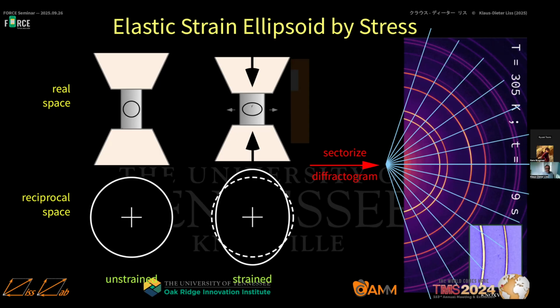In reciprocal space, remember, it's 1 over d or 2 pi over d. That means it becomes shorter in real space in the vertical direction. It becomes longer in the reciprocal space direction, and vice versa. So in the horizontal direction, it becomes smaller. The scattering vector becomes smaller. And what we do, we sectorize the Debye rings. So this is just a little bit less than half a space of diffraction recorded, because we had 2 detectors. I don't show the other one. And what we do, we sectorize here in these 7.5 degree sectors in this case, and then look to the shift for each individual of them. Then we should see the ellipsoid.